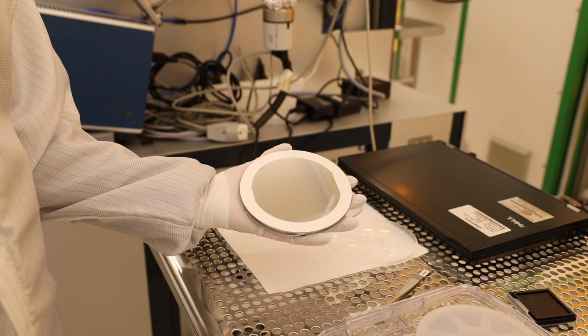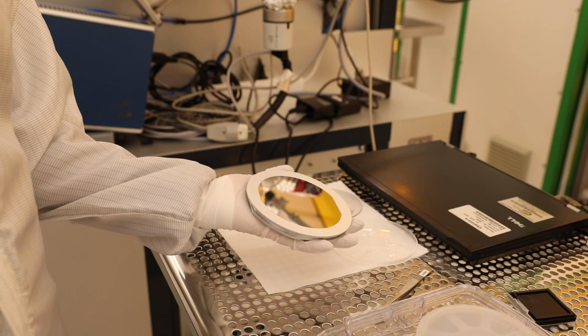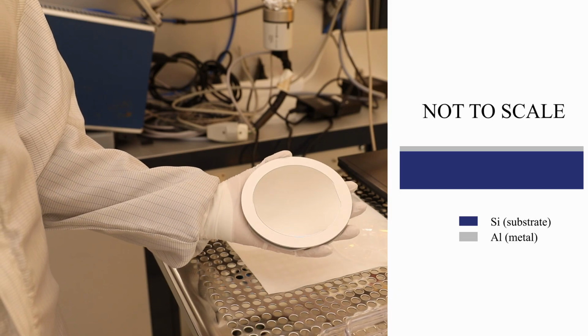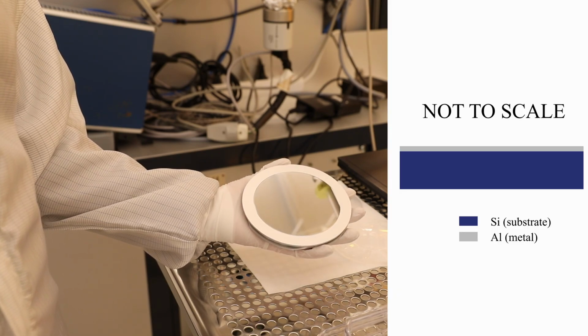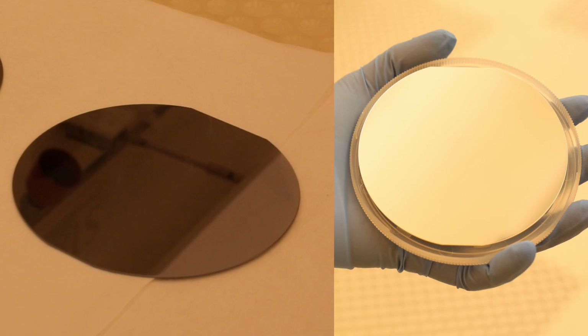So this is what a sputtered aluminium film looks like on a wafer. The film is so thin that we wouldn't be able to really see it looking at the wafer from the side, but looking at the front of the wafer, we can see how the previously dark gray color of the bare silicon surface has been replaced by the mirror-like finish of the aluminium film.